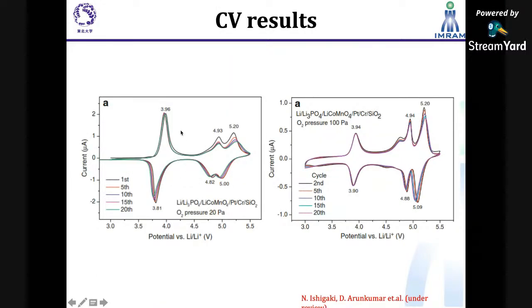However, we could not achieve the complete performance in the 5 volt range. What we expected is to have a high capacity in the 5 volt range, but when we first developed the battery, the capacity in the 4 volt region, that is at around 3.8 volt, is due to the manganese reduction and oxidation reaction. But we need the reduction oxidation reaction of cobalt. But in this case it was not possible.